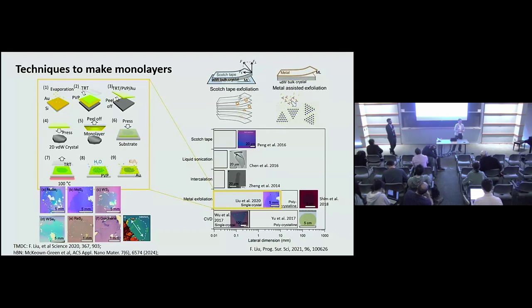Because the HBN van der Waals interlayer force is so much weaker than the HBN intralayer bond, it is more likely that it will crack just to a very thin depth, and then propagate along the van der Waals interface instead of going deeper.